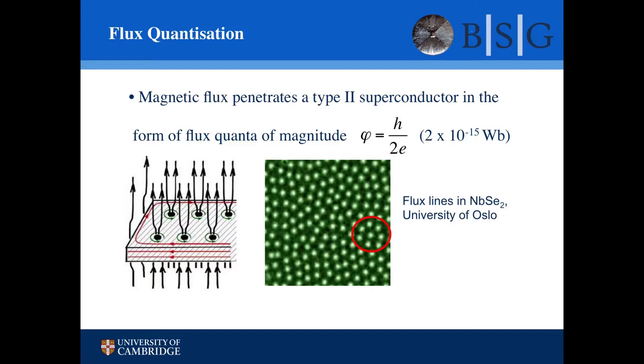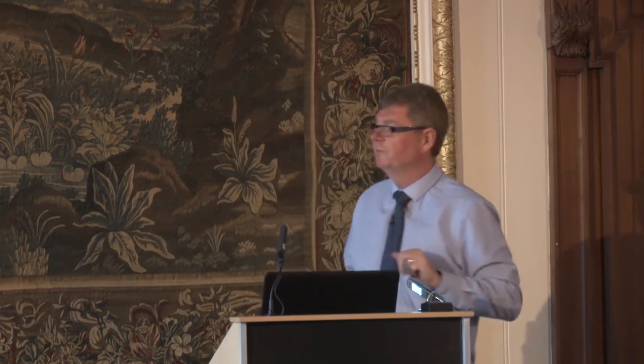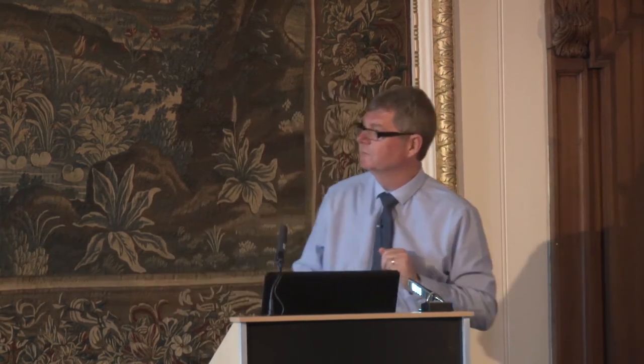We apply the magnetic field, it penetrates the superconductor, you decorate it with something magnetic, and you see this beautiful array of individual dots. Each dot is a flux line looking through the material. And you can even see we get this nice hexagonal pattern here, which tends to tell us that the magnetic flux lines are free to interact with one another. There's nothing stopping the motion of these flux lines. So if you're a physicist and you want a nice pure material with no obstacles in there, so you get this free movement of magnetic flux, this is what you want to see.